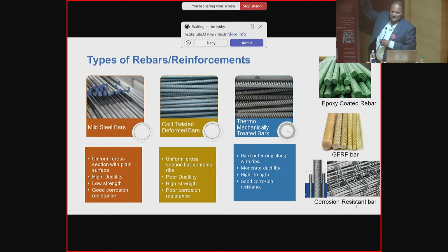The bar is heated and suddenly cooled, made to undergo lower temperatures, that is called quenching, by which the rebar will have an outer layer which is very strong. Suppose you have a 25 mm diameter bar, there will be an outer layer which is not visible to your eye. It will be about 0.1 times the diameter of the bar. That gives the strength. The inner core is giving the ductility. So both strength and ductility can be achieved by using a TMT bar, which is predominantly used today.